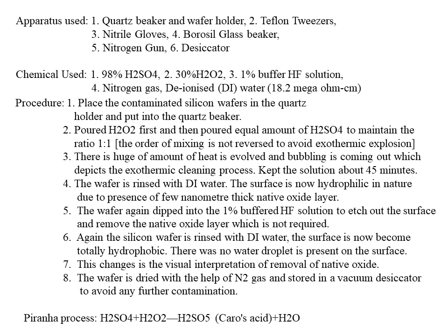There are a few precautions, just to avoid mixing in the reverse direction. The first one is H2O2, then H2SO4. We must use the quartz beaker and quartz wafer holder to avoid any type of explosion. Normal borosilicate glass cannot withstand this high temperature, and we have to use nitrile gloves for the entire process, just to protect our hands.